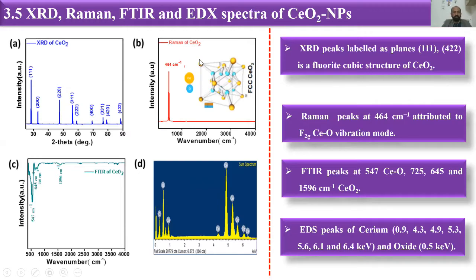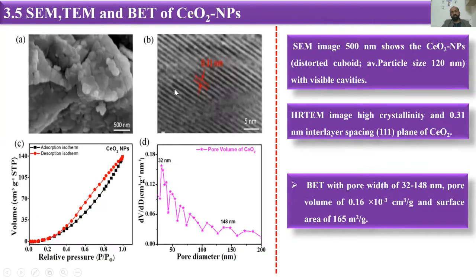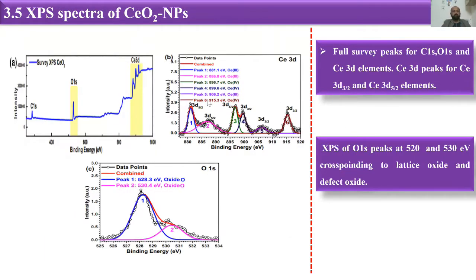So we have got the Raman spectra and FTIR spectra of our cerium nanoparticles, and we have done the EDX spectra of our particles, and all the peaks mentioned here are from the cerium nanoparticles. Then we have done the SEM, TEM, and BET, and we have got the TEM and BET with BET pore size. I have mentioned all these values here, so I don't want to go into detail. Then we have done XPS spectra of our cerium nanoparticles, their full survey spectra, and their Ce 3d and O 1s spectra, and all the peaks from the cerium nanoparticles are present.